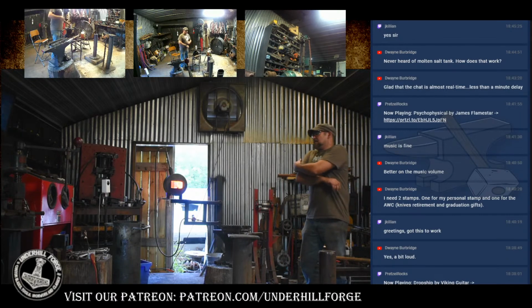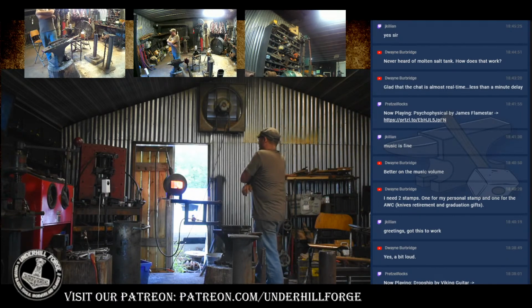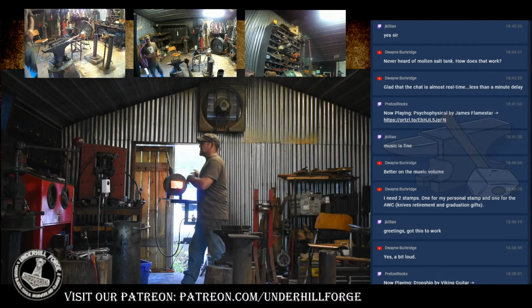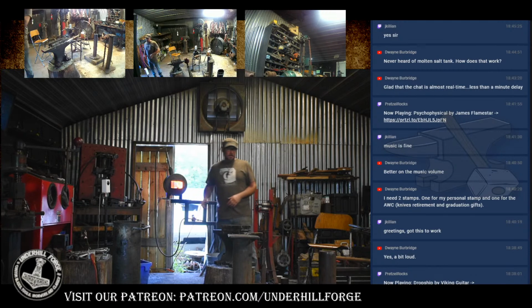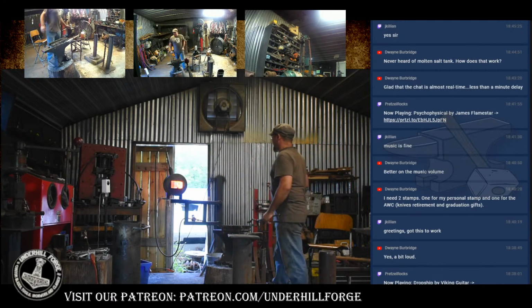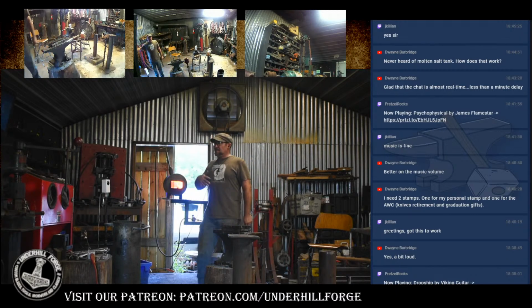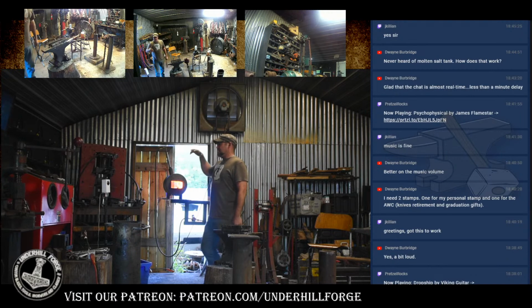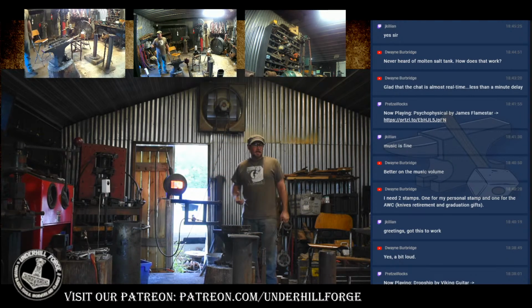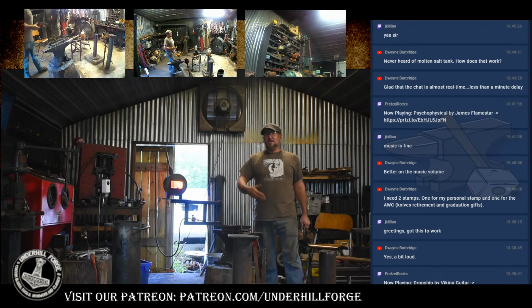What's really nice about using the salts is that when I'm using the high temp salts, we don't get any of the oxidation that we get in the forge. With the low temp salts, I can come out of the forge or out of the electric heat treat oven, and I can do what's known as wrench quenching. So essentially I'm quenching at a high temperature, but very, very fast.